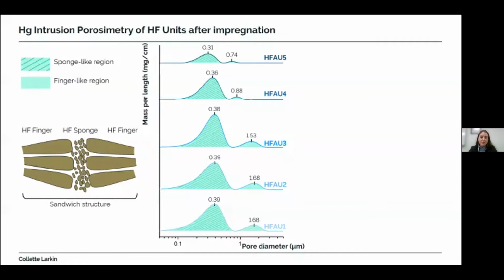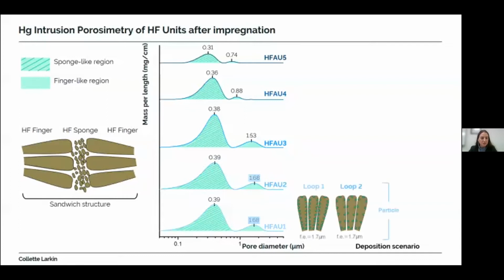And if we pair these results with the SEM and EDX images shown previously, we have identified 3 possible deposition scenarios that the 5 hollow fibre adsorption units can be separated into. So after 2 impregnation loops, the pore size distributions are approximately identical to that of the after 1 impregnation loop, suggesting that the calcium oxide deposited didn't fill the fingers nor reduce the opening to the fingers. Therefore, we propose that the hollow fibre adsorption unit 1 and 2 exhibited the partial deposition scenario.